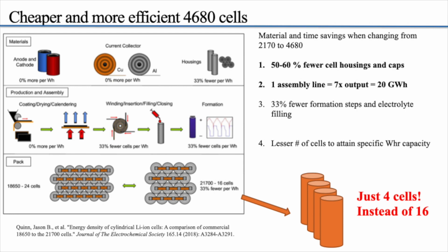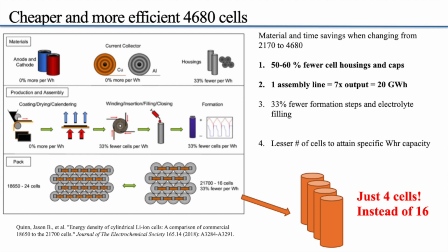I think that changes things. You estimate that they're using 50 to 60% fewer cell housings and caps, right, with this new form factor. That's just a rough back of the envelope guess. It's pretty remarkable. It should take them less time to produce each pack, correct? Exactly, because now they don't have to fill as many. See, in the case of 18650, they had to fill 24 cells, electrolyte filling, formation, winding, but they just have to do it for 4 cells, and the machine doesn't have to stop for installing the tabs on each of those jelly rolls. So only 4 cells. So the time reduction is massive, and the material reduction is massive.